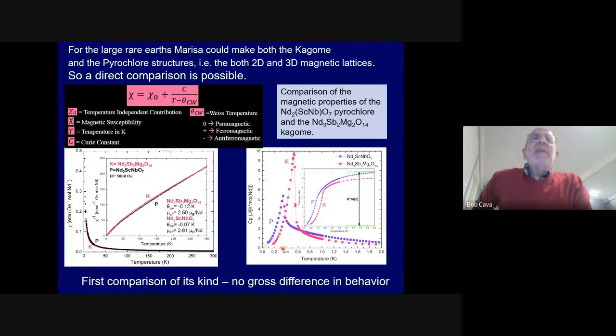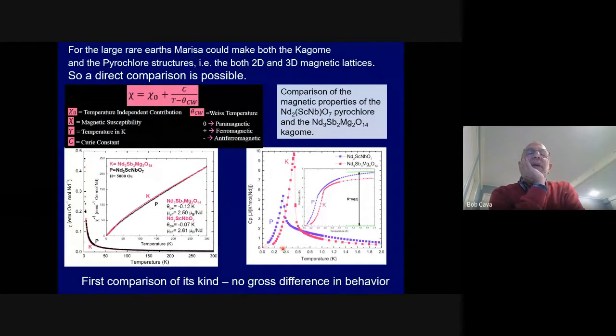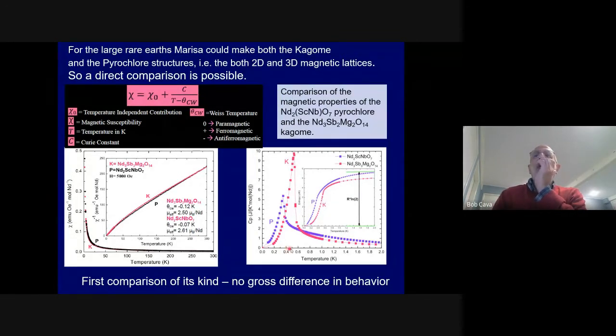And this has to do with the fact that the unpaired electrons in the rare earths are in the f orbitals. And those f orbitals are very close to the nucleus. They have a high angular momentum. They are just not very strongly interacting with each other. So even though you can get magnetic ordering in these things, you need special equipment to get to such low temperature.